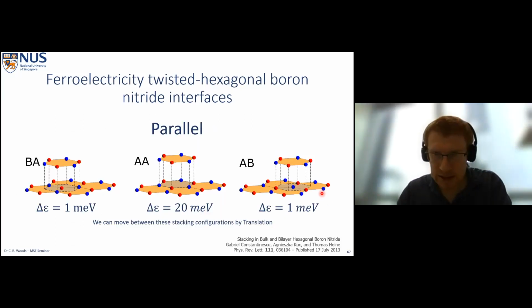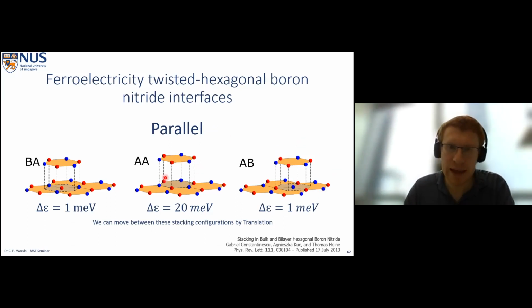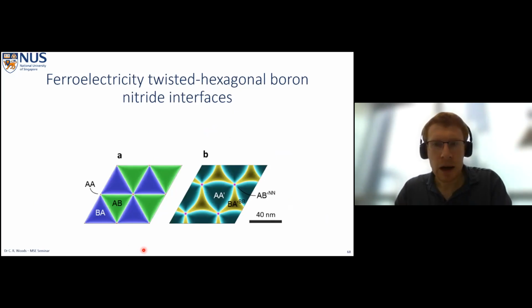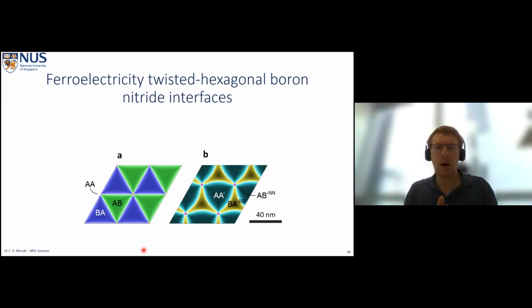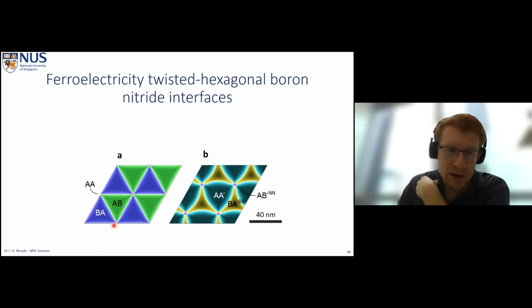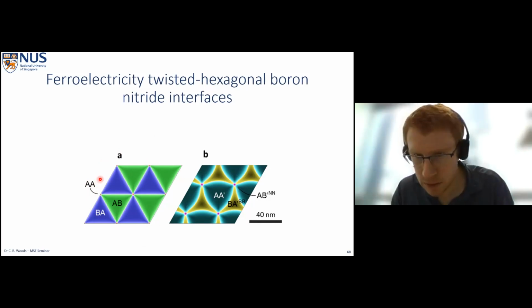Okay, so this is just a summary of the energies we saw before. For AA, very unfavorable, very high energy stacking configuration, whereas AB and BA have the same energy. So we can do some theoretical calculations to relax this system and find out how the interface will organize itself. And what we find is that for the parallel configuration, we find exactly what I've just described, that AB and BA configurations share the same amount of the unit cell, and that the AA stacking configuration is compressed into these small areas because the interface really doesn't want to have any AA stacking at all, because it's energetically unfavorable.